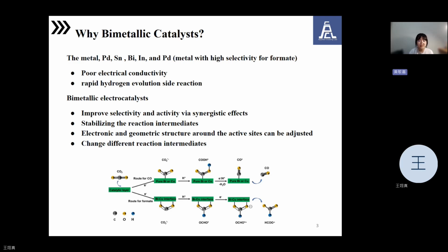The picture below is the mechanism of the reaction pathway for CO and formate production from CO2. At the top, the pathway shows CO2 being reduced to CO on the pure Bi or Cu surface. The reaction proceeds through the formation of the COOH intermediate, which is reduced by accepting electrons and protons to form CO. At the bottom, the alternative pathway shows CO2 being reduced to formate ions on the BiCu bimetallic interface. The reaction first forms a CO2 intermediate, which then goes through an OCHO intermediate, followed by electron transfer to form HCOO- ions.